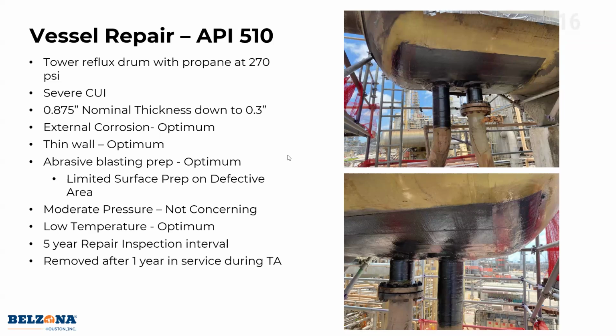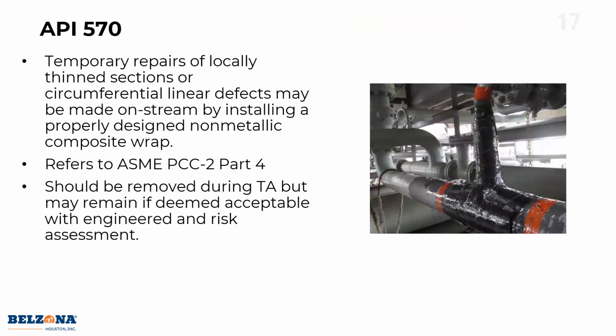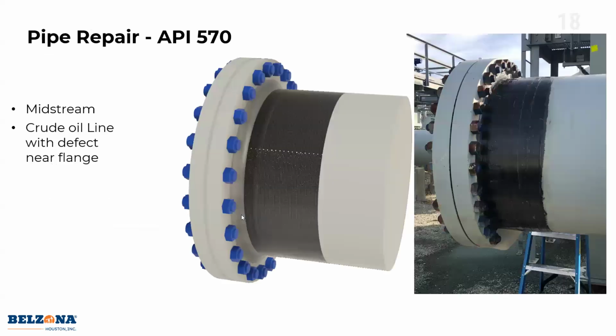We don't have to worry about any more CUI, and so this worked out really great for them. They were able to remove it during the turnaround. It wasn't the easiest to remove. They're not made to be removed, but they were able to do it and do their weld repair. So finishing off with pipes, temporary repairs can be done, once again, as long as they're compliant with the ASME standard. They should be removed during the turnaround, but may remain if deemed acceptable with engineered and risk assessment.